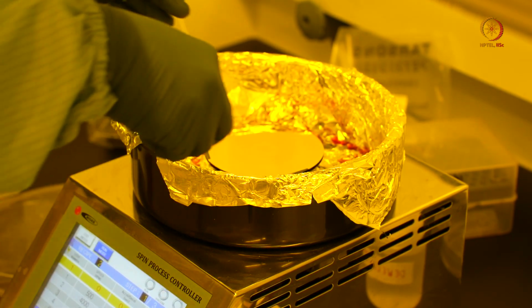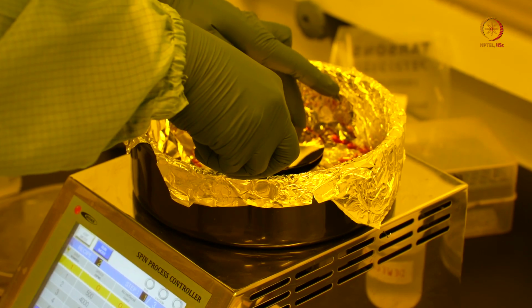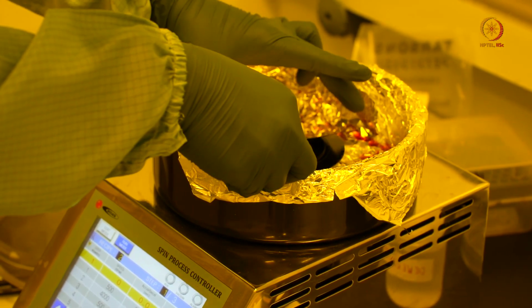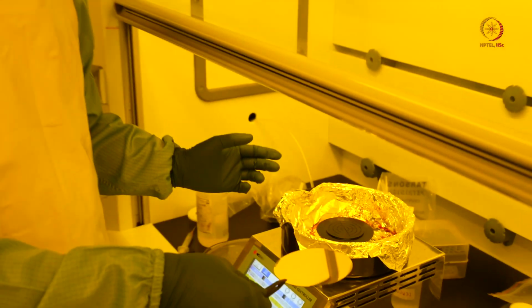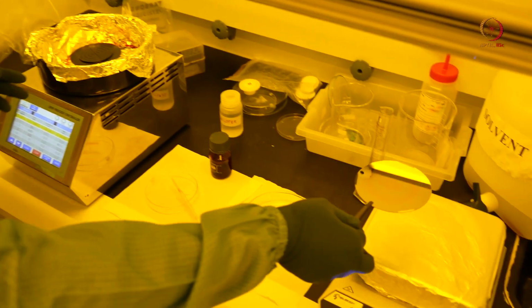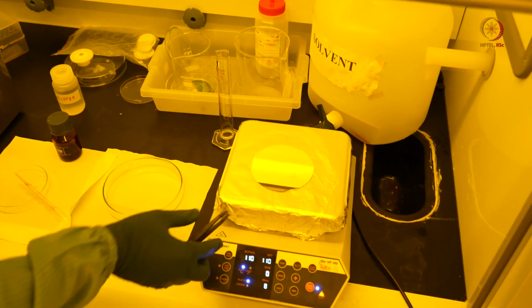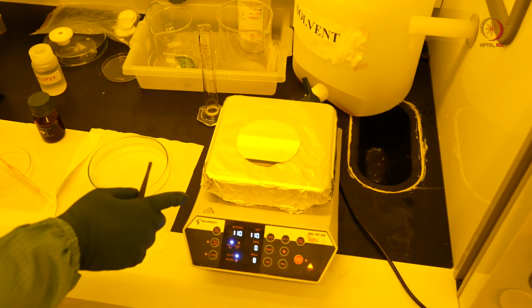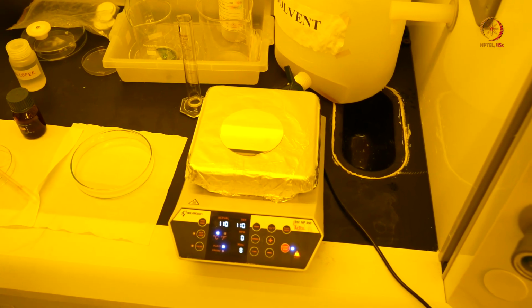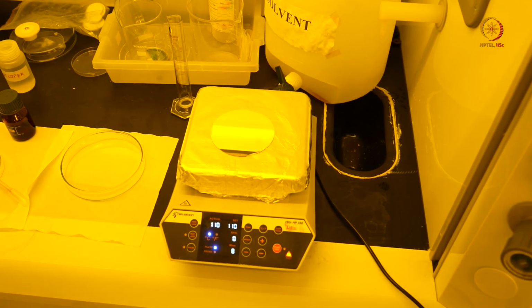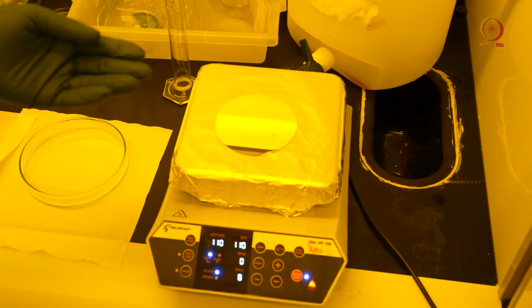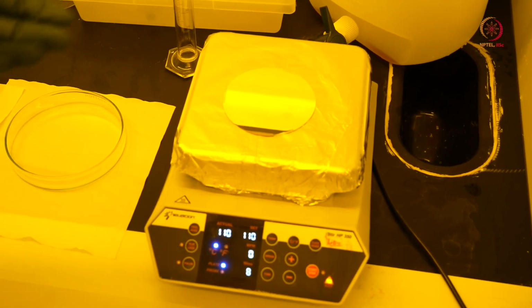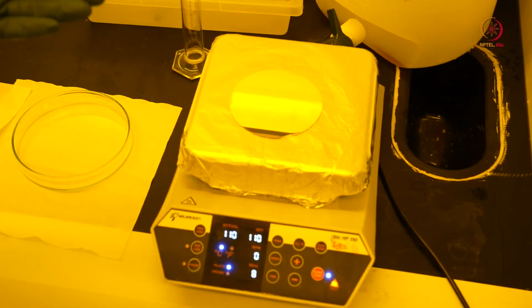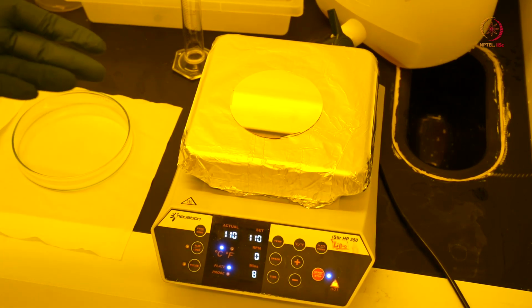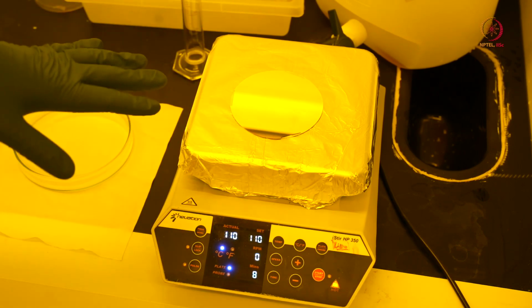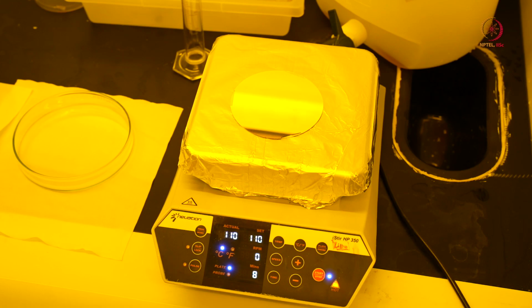So I'm switching off the vacuum and taking the sample out. And we will slowly shift it to the hot plate, which is maintained at 110 degrees Celsius. We have to keep it here for 60 seconds. This step is very crucial in that the excess solvent in the photoresist gets evaporated, and then all we have will be the photosensitive material and the cross-linking polymer available in the photoresist. So we will keep it here for 60 seconds, and then we will go for the next step.